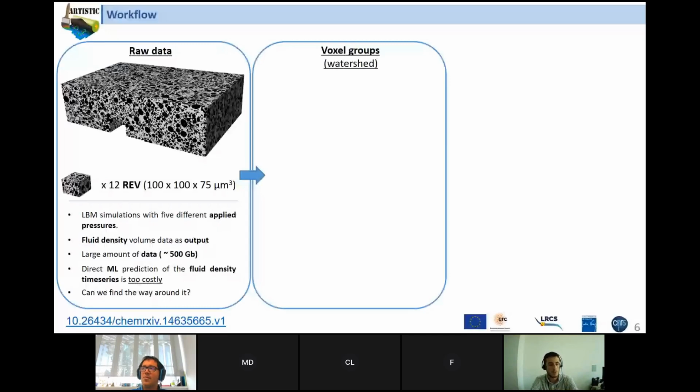Actually there is a whole body of literature around finding these reduced representations of the pore spaces, which are also called pore network models, and which can be built in many ways. So for instance, one way of building these pore network models is to fit spheres into the pore space, and then connect these spheres with throats until you reach a proper porosity for the microstructure. But they can also be built by labeling or grouping pore voxels together given some presupposed rules, right?